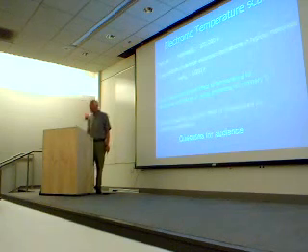Like in an alkali metal, you get essentially a free electron parabola, but the density of states and the specific heat get modified. If you go to a transition metal, it can be modified very much. If you go to one of the systems I'll mention later, it can be 1,000 times what you get out of a band calculation. And that's hard to model. So there aren't good practical ways of using such a theorem.